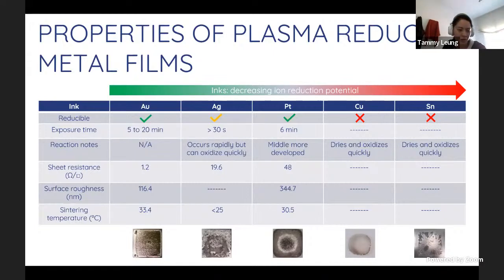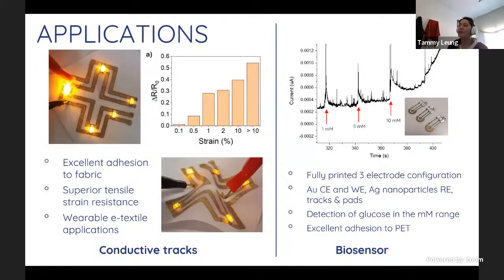For the other inks, such as gold and platinum, we were able to control the oxidation with the oxygen plasma and saw reproducible results across the board. Previous studies showed that argon plasma by itself could reduce a much greater amount of metallic films. However, they saw temperatures of 150 degrees C or above, meaning that thermosensitive substrates could not be used in that case. Once again, this is not something that we saw with our substrates and this technique itself. So once the formulation and optimization were done with the respective inks,